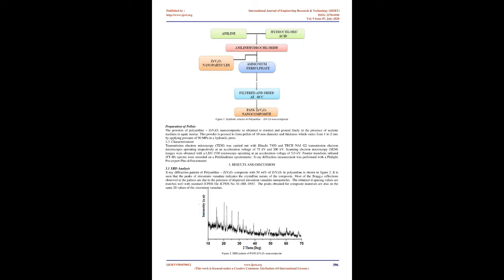The precipitate powder recovered was vacuum filtered and washed with water and acetone. Finally the resultant precipitate was dried in an oven for 24 hours to achieve a constant weight. Lastly, all the synthesized composite so obtained above is crushed into fine powder in an agate mortar in the presence of acetone medium. The synthetic scheme is given in figure 1.